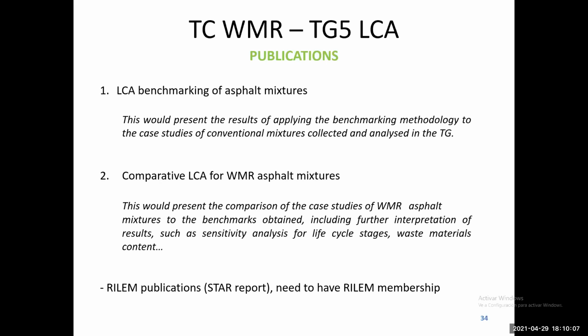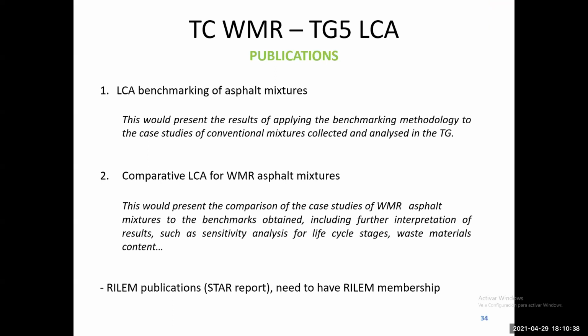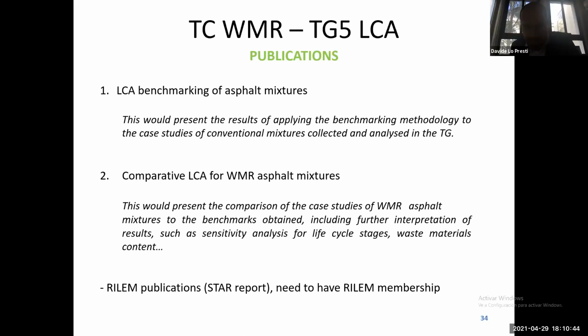Yeah. So one way to know these emissions is to have contact with the people that have placed the filters on the chimneys of the asphalt production plants, which is a bit difficult. The other way is to produce these mixtures in a lab environment in smaller quantities, and then measure the fumes there, which is way easier, and then make them proportionate to the temperature and the magnitude of the mass. But once you measure, can you introduce them in the LCA?